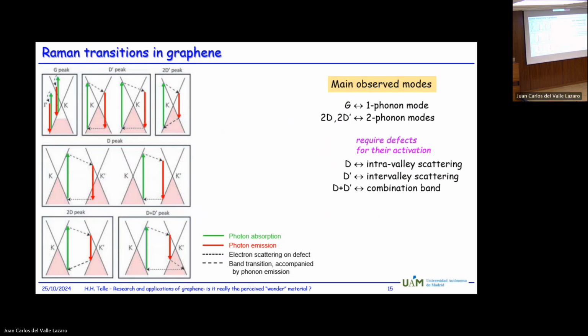I do not want to go into details, but there are basically different main modes in the system, because we cannot any longer talk about energy levels of individual particles or atoms, but it is embedded in a crystalline structure. So therefore, we have to talk about, in particular, phonon modes in the system. And as I said, there are three particular modes which are common to pure graphene. But if you contaminate it, and there's no way around contaminating the system, then there are further modes which are related to defects in your system.